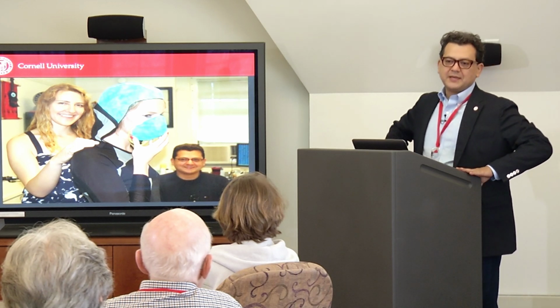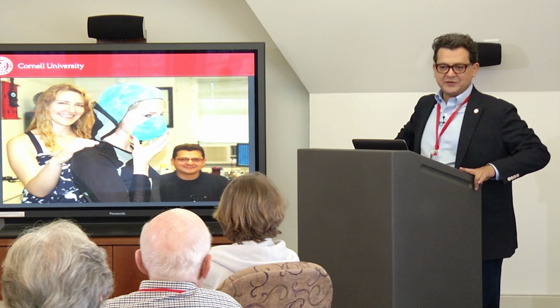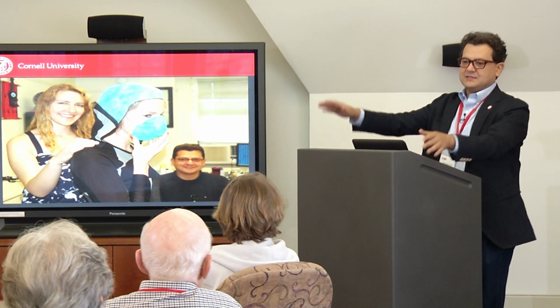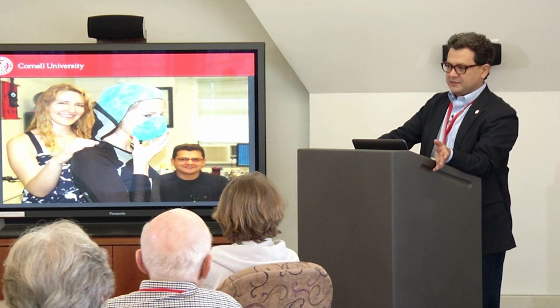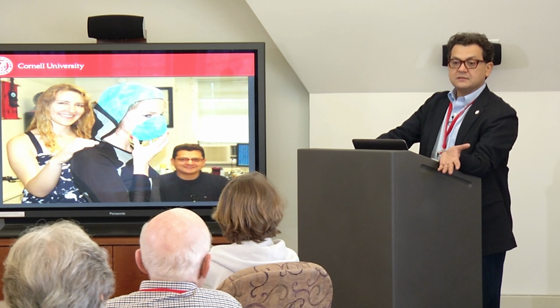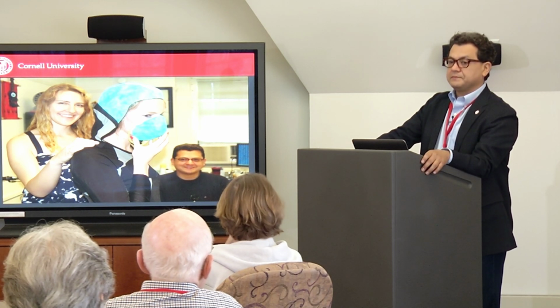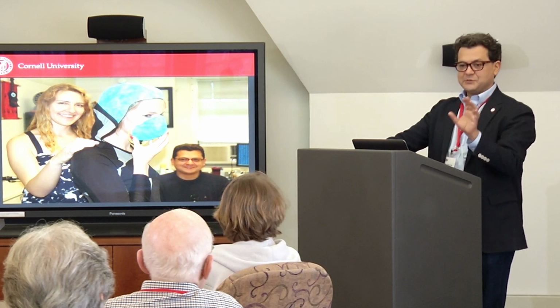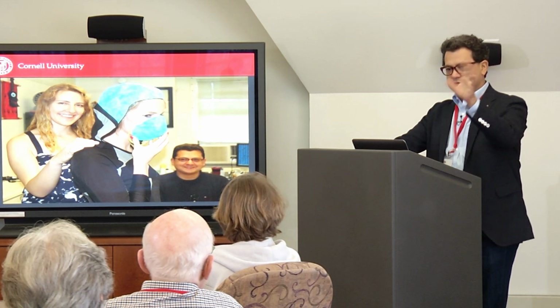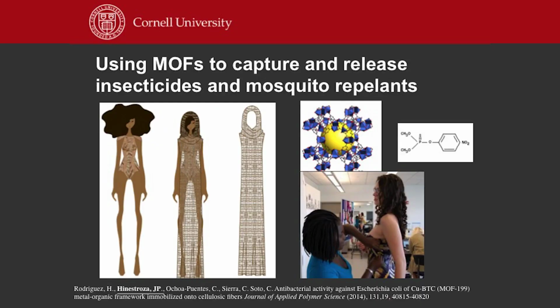And then I have a postdoc from Kenya, and he says the same, yeah, malaria is very common, and we use these mosquito bed nets, but then the insecticide in the bed nets is released, and then we are not protected anymore. So we would like to capture the insecticide and then release it when the mosquito is more active. And that was a very good project, because then my student and my postdoc decided to use these molecules to capture the insecticide in large amounts, so the mosquito bed nets will last longer without being refilled.